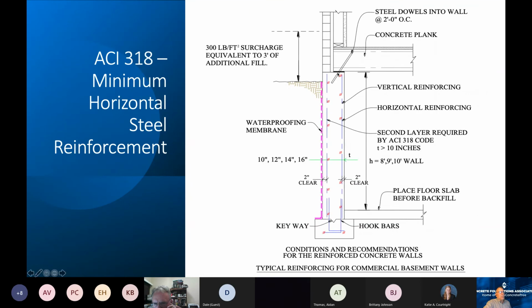The problem is, though, when you step into the commercial code, and this is a wall section that's affected by the commercial code, not only do I have double mat steel, but that's the most economical way for me to get the steel percentage high enough to meet what ACI 318 says is my minimum amount of steel. And so you can see the 2 different layers, and I think this is an 8-foot wall also, and I've got 6 bars on each side, so 12 versus 3, because I'm accounting for the fact that the wall length is much longer.